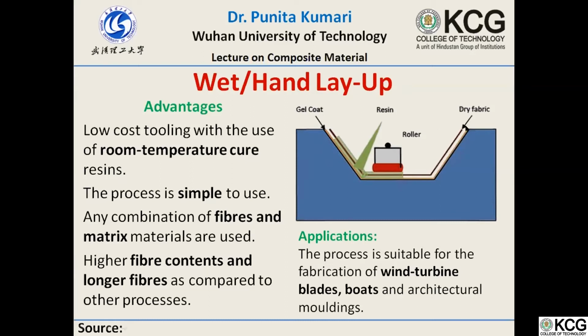Then apply the fabric of the fiber, whether you want glass fiber or carbon fiber. Then apply the resin. Then use the roller and make it uniform. The resin should be uniform. Then apply the fiber fabric again, based on the thickness. Depending on how much thickness of the composite you want, you can make 15 layers or 16 layers or 20 layers. After that, just leave it for 12 hours or 24 hours. It depends upon the resin curing time, and this curing time is given by the manufacturer, because they know when the chemical gets cured.